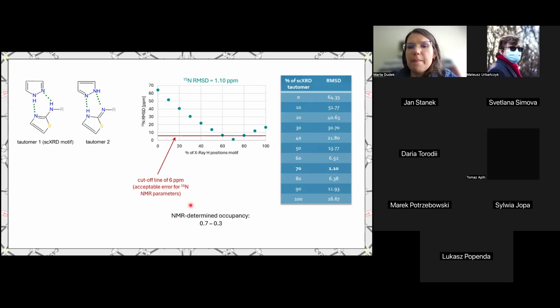So this is one of very rare examples of NMR-determined occupancy. We can now show to all the crystallographers that, look, we can do with NMR what you can do with single crystal X-ray diffraction measurements. We can actually determine the occupancy of two different sites in a crystal. And this phenomenon is not visible because of the low electron density on hydrogen atoms, especially between those two electronegative atoms. We do not see them through single crystal X-ray diffraction.